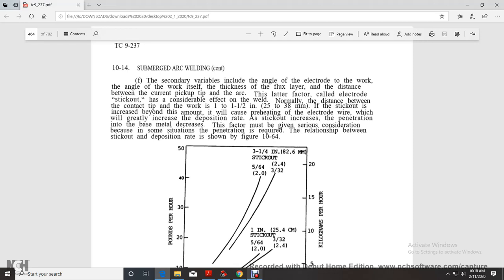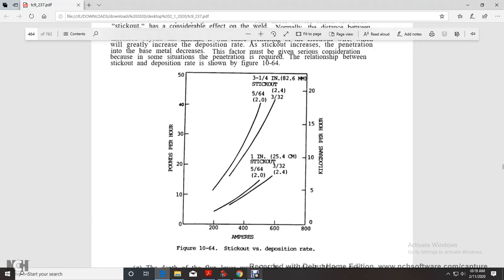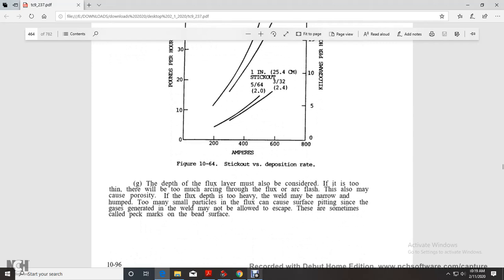The decrease of the factor must be given serious consideration because of situations where penetration is required, due to the relationship between stick-out and deposition rate shown in figure 10-64. This figure shows stick-out versus deposition rate in amperes, pounds per hour, and kilograms per hour, for 3.25 inch stick-out and 1 inch stick-out.